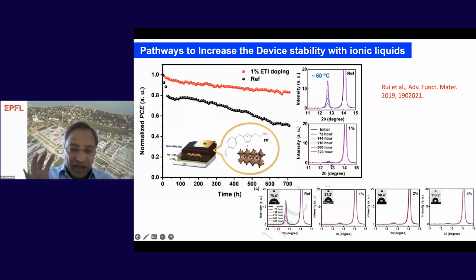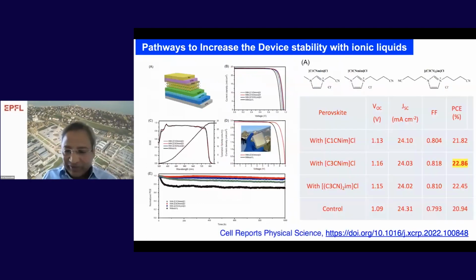But as I mentioned, this hydrophobicity, we can measure with contact angle measurements. This is the reference sample, which has a contact angle of 75 degrees. When we add 1%, the contact angle increases to 87. If we increase the ionic liquid content to 2%, it goes to 98 degrees. And if it's 4%, you can see the contact angle is increasing significantly. So the purpose here is the ionic liquid is protecting the perovskite by the hydrophobicity of its nature.